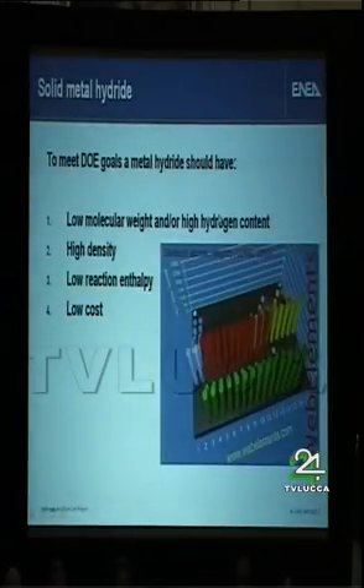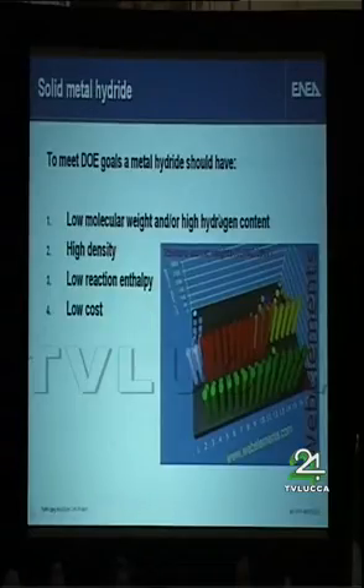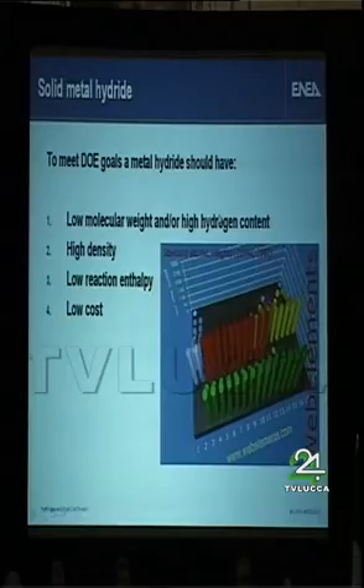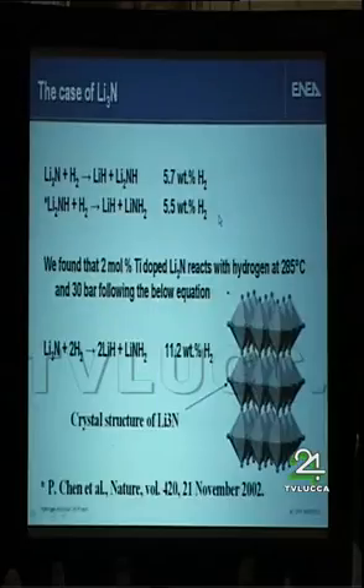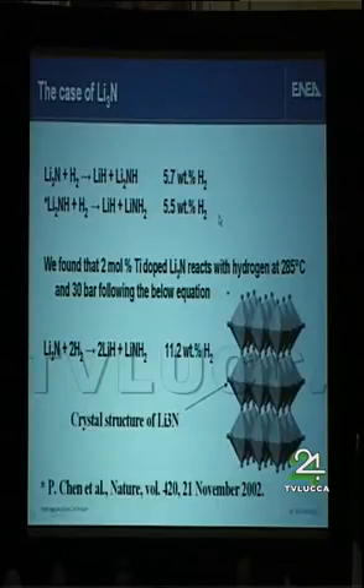To meet the DOE goals, an ideal metal hydride should have low molecular weight and high hydrogen content in moles of hydrogen per mole of metal, high density, low reaction enthalpy, and low cost. Now I want to show you the case of lithium nitride. It was shown that lithium nitride can reversibly cycle about 5% of hydrogen at 285 degrees, and we found that doping lithium nitride with titanium, 2 mole percent, it's possible to cycle about 10% of hydrogen per gram of lithium nitride.